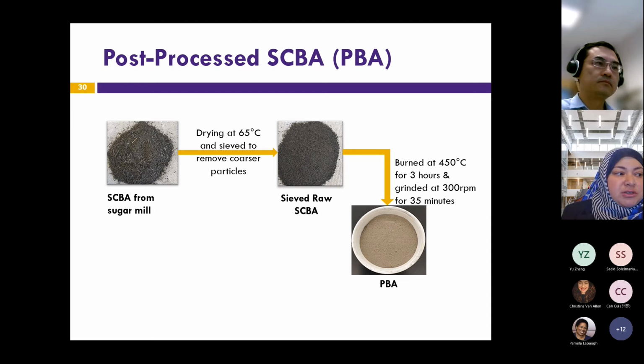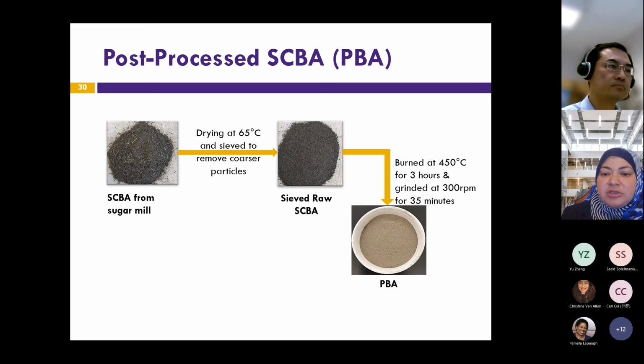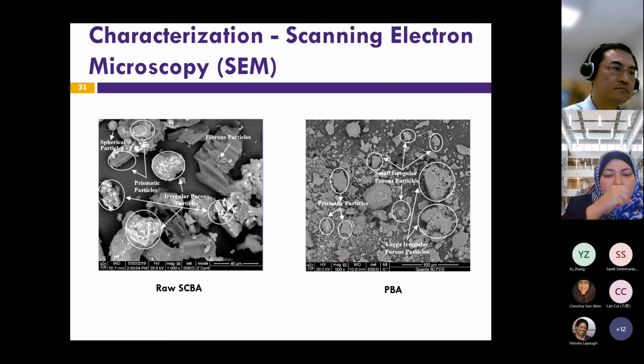If we further process it by burning it at 450 degrees Celsius for 3 hours, then grind it at 300 RPM for 35 minutes, we get what we call post-processed bagasse ash, and this is what we use as cement replacement. We have done a lot of work in terms of identifying the strength activity index and the chemical composition of the bagasse ash to see that it's suitable for placing in the cement.